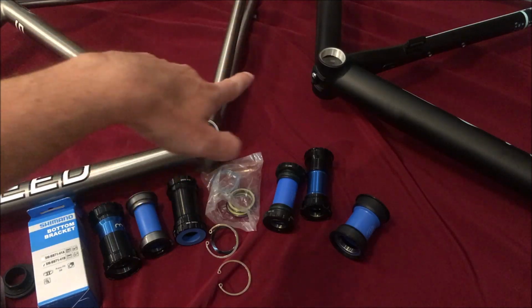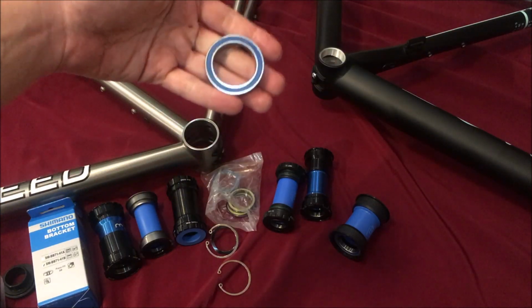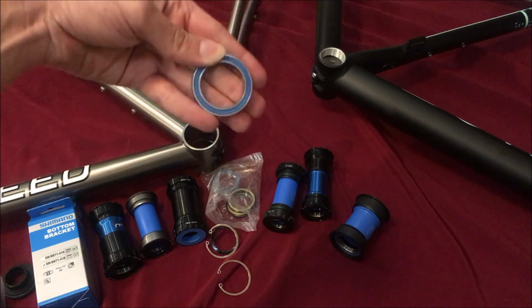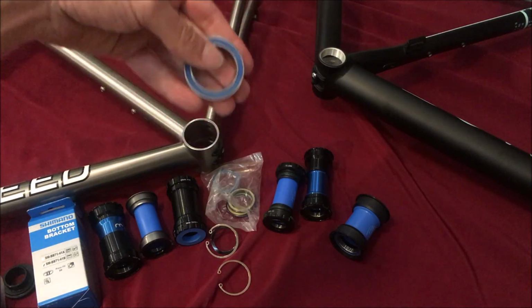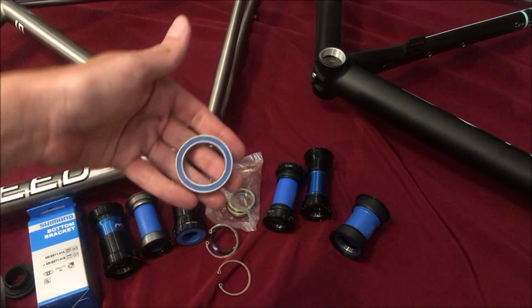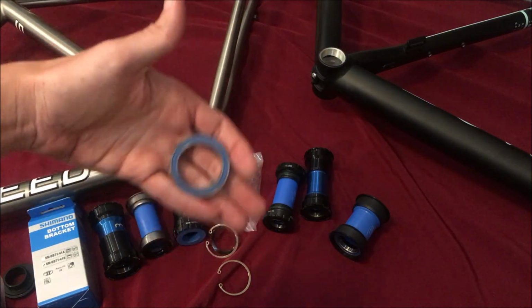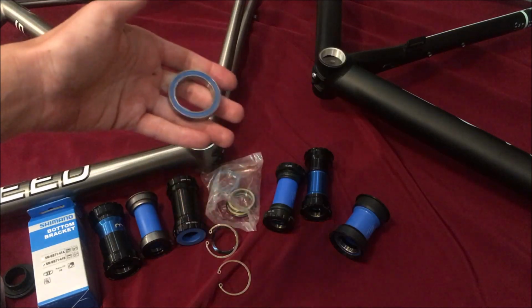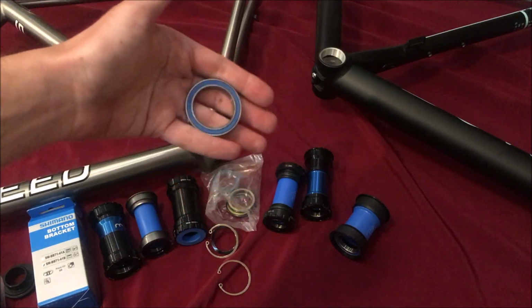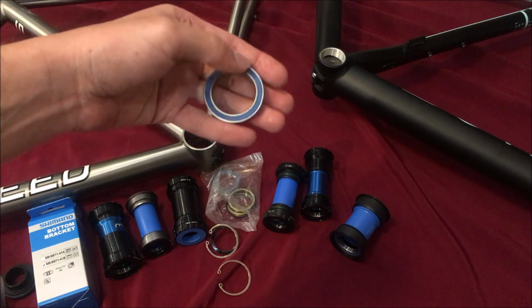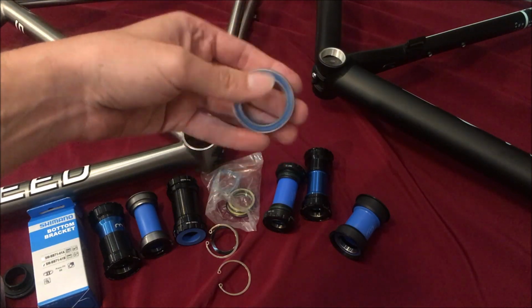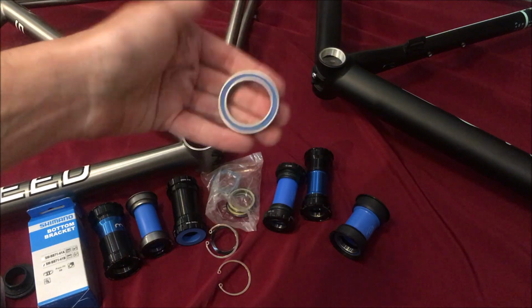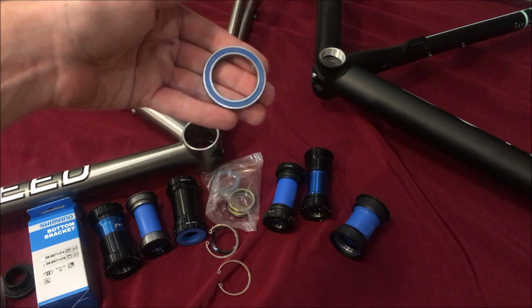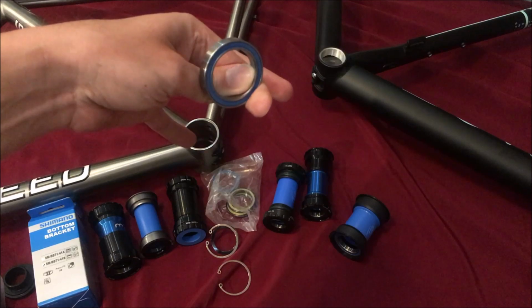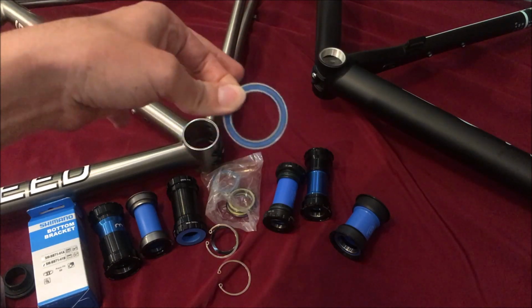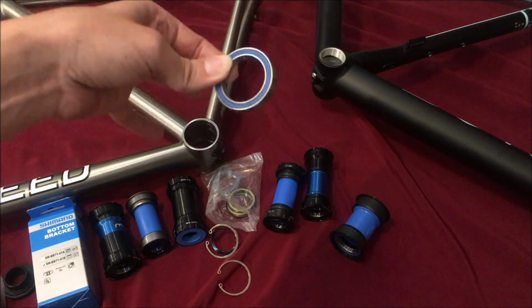And because it's not threaded in, unlike the threaded bottom bracket over there, which is threaded in and secure, these can move around. So again, you get misalignment within the frame, and a lot of people complain, especially about the Cannondale bikes, that they creak like hell. The reason is that you've pressed a steel bearing into an aluminium frame, a stronger material into a softer material. And then as you remove these and press them in again, each time you come to service the bike and replace the bearings, and especially in the Allez, which tends to retain a lot of water in its bottom bracket, these rust really quickly.